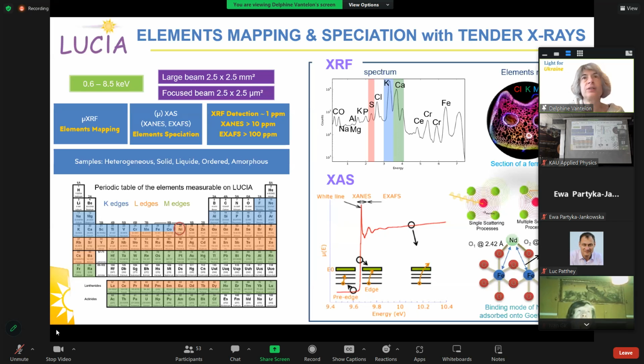So, LUCIA is the tender X-ray beamline of Soleil dedicated to element mapping and speciation by X-ray fluorescence and XAS coupling. So it means that we are working in the 0.6 to 8.5 keV energy range, and the beam can be as large as 2.5 millimeter or focused down to 2.5 micrometer. Then we can map, in a heterogeneous sample, the elements that are reported in this Mendeleev table. You can see an example of map here, and at specific locations of the map, we can collect the XAS, either XANES or EXAFS, to obtain the speciation of the element, its oxidation state, and electronic and atomic local environment.